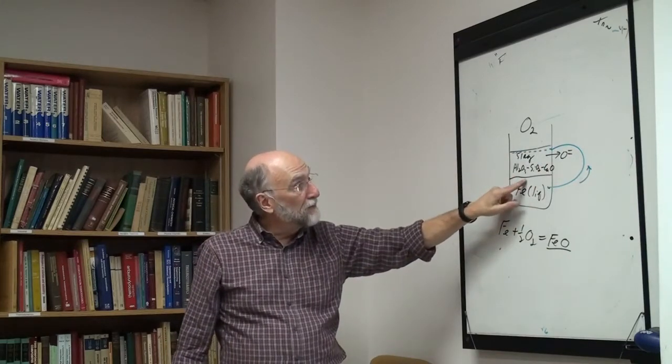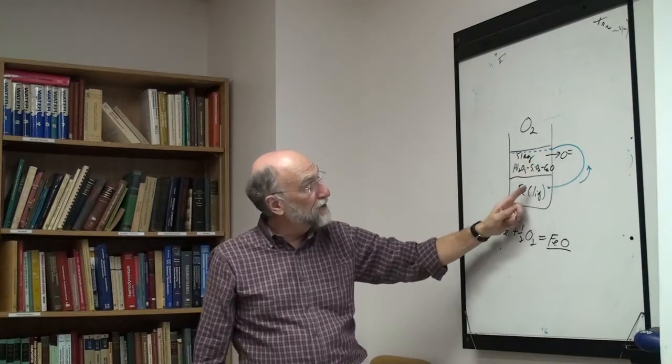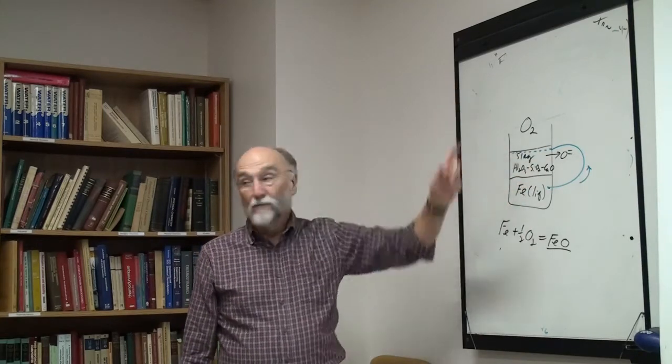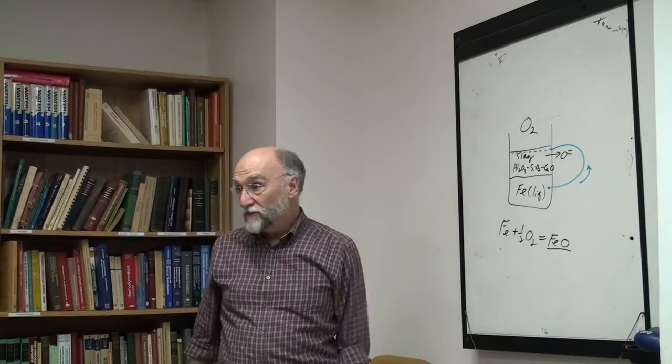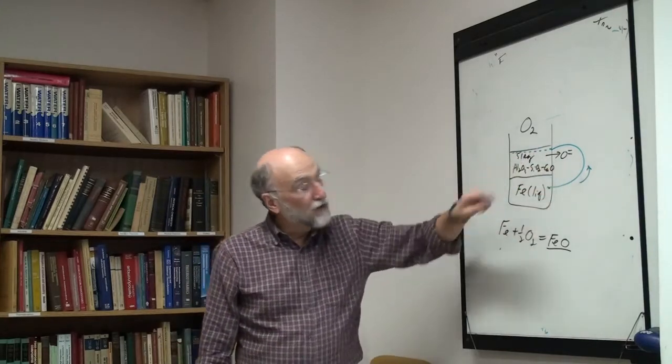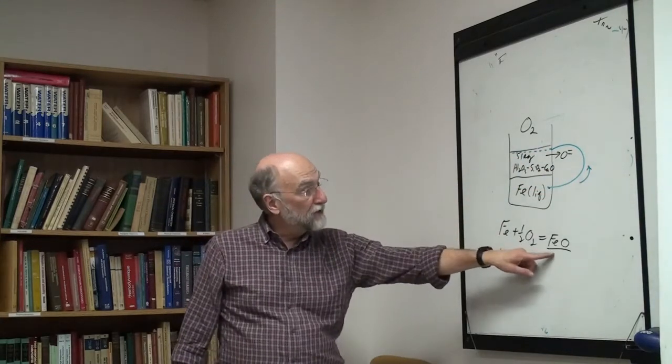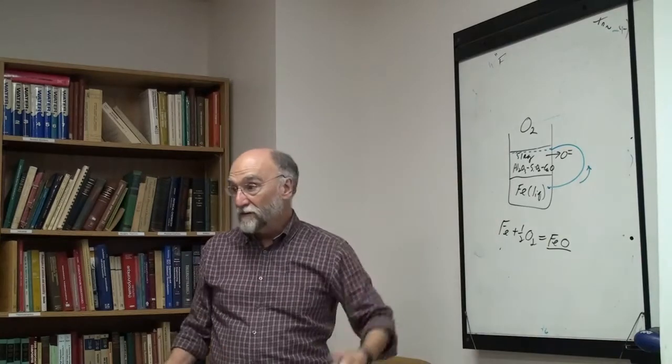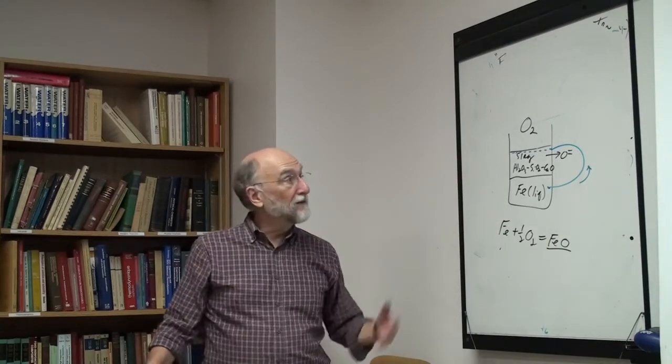Or an iron atom loses 2 electrons to the external circuit, becomes an iron ion, and moves very quickly through the slag. So the minute you put an external circuit here, you'll find the formation of FeO is very, very fast, indicating the ionic nature of the slag.